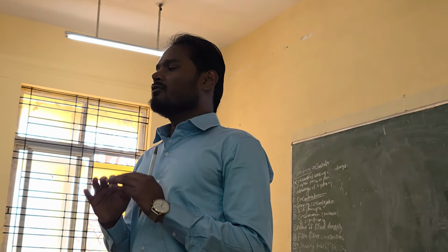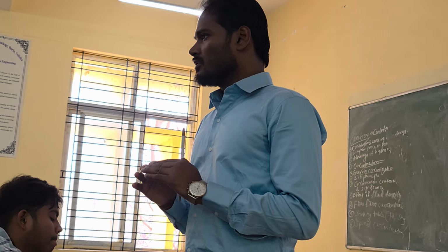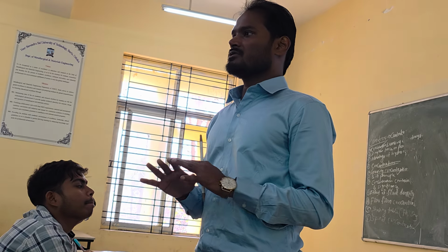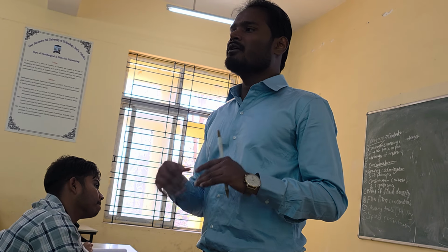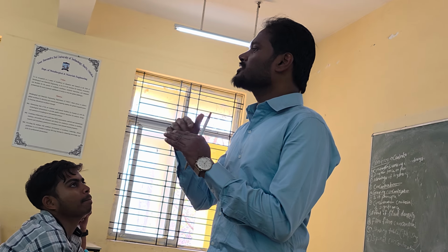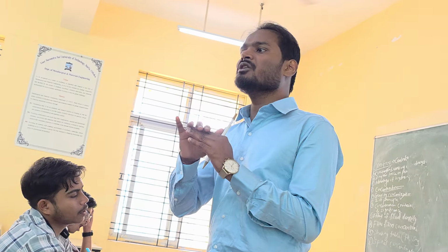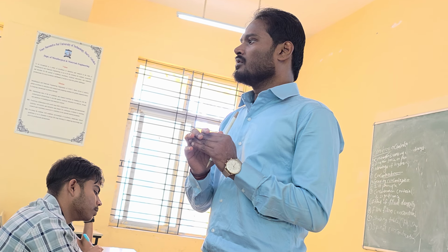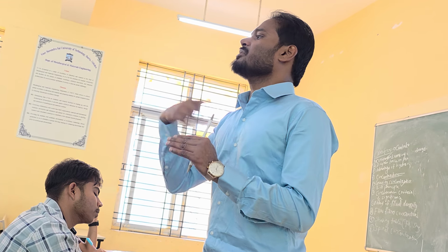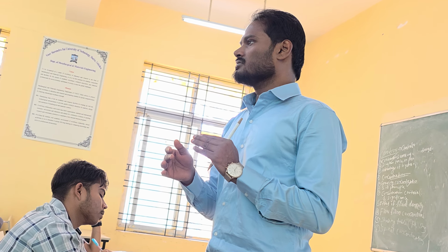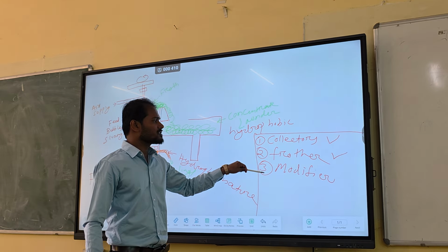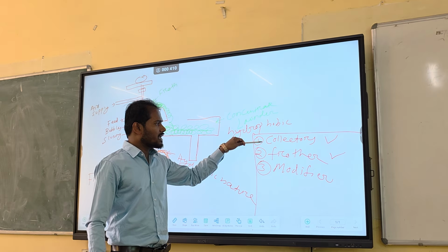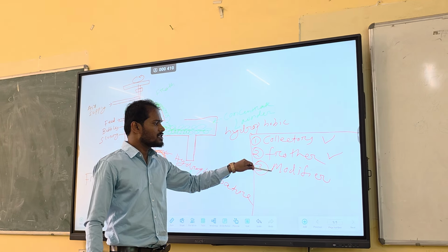So when we want to do froth flotation, we need chemicals. And why do we need chemicals? Because chemicals will change the surface chemistry of the mineral, like from hydrophilic to hydrophobic, or they may increase the stability of the air bubbles. So all these have some function, right? One is collector, one is frother, one is modifier.